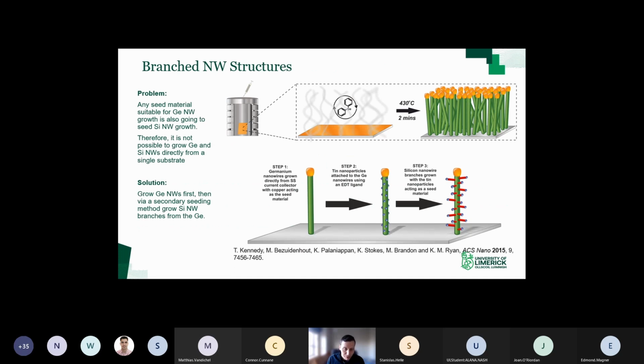One of the issues we had was that we wanted to grow germanium and silicon nanowires individually on the same electrode, same current collector, but it's difficult because anything that will seed germanium growth will also seed silicon growth. So we couldn't just pattern different seeds and grow them individually, because if you tried to grow germanium only, all the seeds would be used up. So rather than grow silicon and germanium from the current collector individually, we grew heterostructures. We grew the germanium nanowires first, and then we patterned those with tin seeds. We attached tin nanoparticles using a thiol ligand, ethane dithiol. That attached the tin nanoparticles, and then we were able to grow silicon nanowires from the germanium stems. So we had this branch structure.